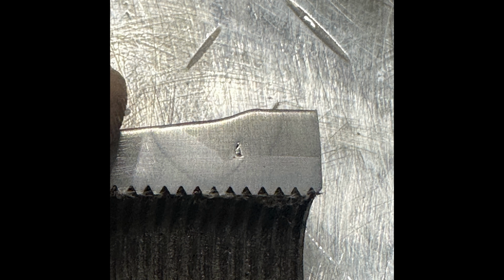Also, I ran a little bit less amperage, probably around 160 amps, and that would have likely made a difference. And also, I'll be honest, I didn't prep the surface of this tube. I should have ground it down rather than leaving the dry cut saw marks, so that could have also contributed towards this. And it goes to show, even with TIG, you can end up getting bridging and lack of fusion on something like this. So keep the material clean, go slow enough and run enough amperage and be smart about it, or you can get this.